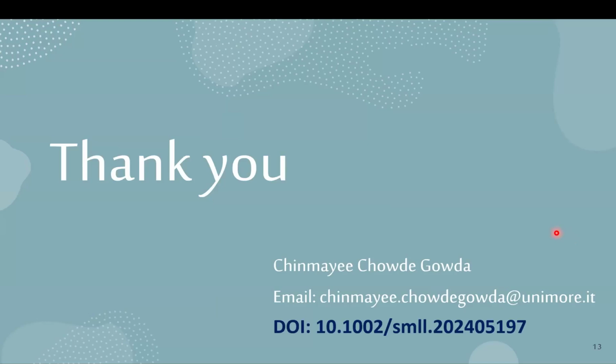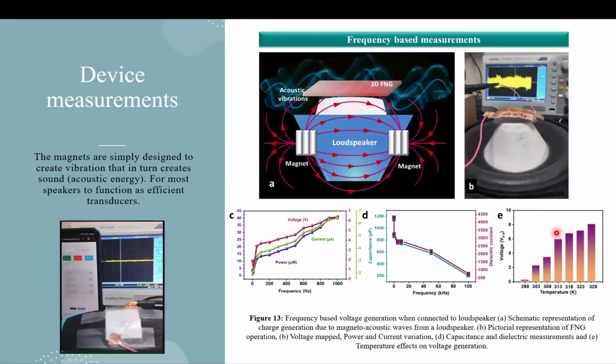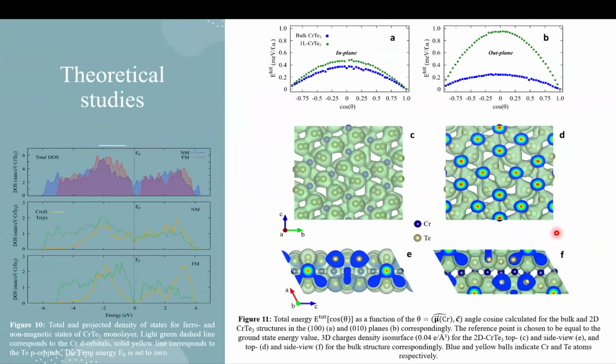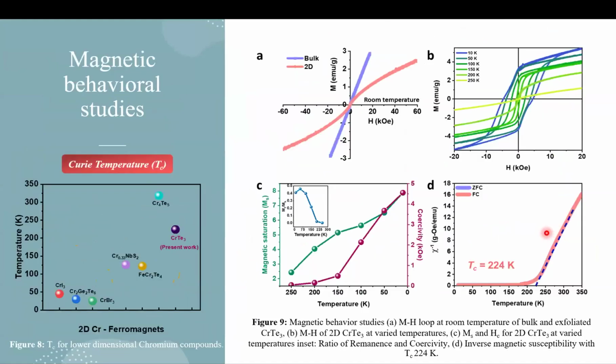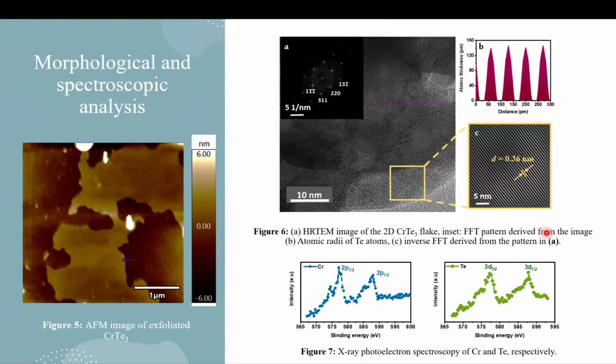It actually depends. The magnetic field varies with the changing layer thickness, but in this particular study, I have just compared the bulk with 2D. But to continue the studies, we are exploring different layer thickness flakes in MFM, and we are trying to study how it varies. After a particular number of layers, it starts behaving as bulk again. So until 3 to 4 layers, it is okay, and after that, the behavior is almost as the bulk.